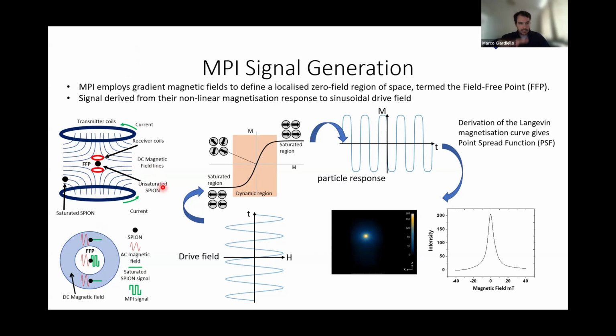By creating large gradient magnetic fields, you have a point where your SPION is not saturated. You oscillate the field against that. So only in that region your particle oscillates, and from that it's picked up by the receiver coils and you generate an image.